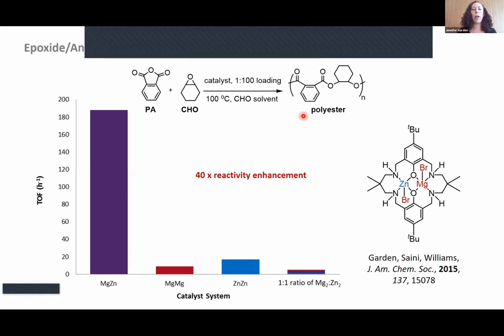And the bar on the left, you'll notice, is significantly higher than these other three. And this is because the purple bar represents a catalyst that has two different metals in its structure. In this case, it's magnesium and zinc. So by incorporating these two different metals and having them close to each other, we can improve the catalyst performance compared to the equivalents where there are either two magnesiums, two zincs, or a mixture of the dimagnesium and the dizinc complexes. So by using these heterometallic complexes, we can enhance the catalyst performance.